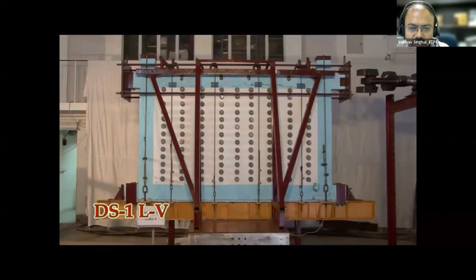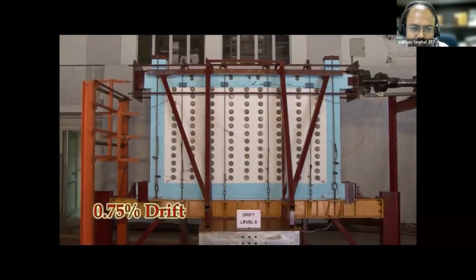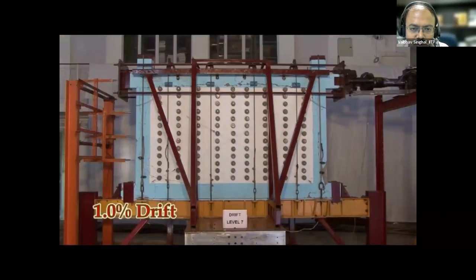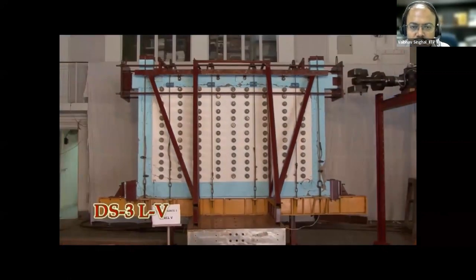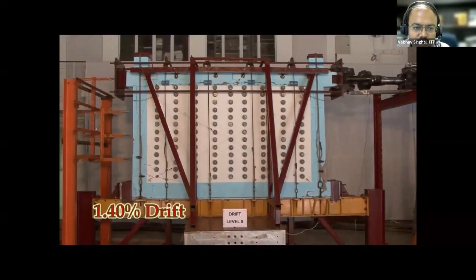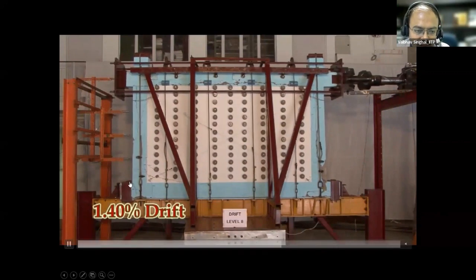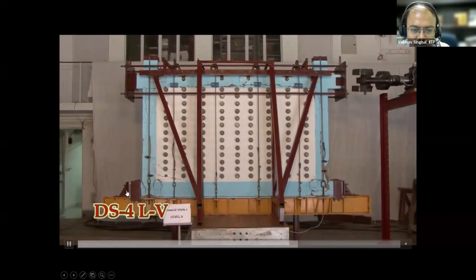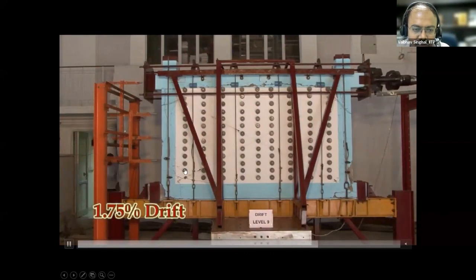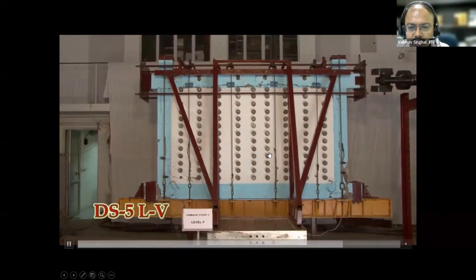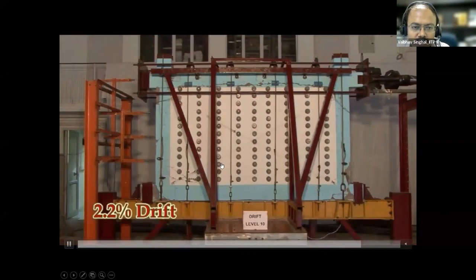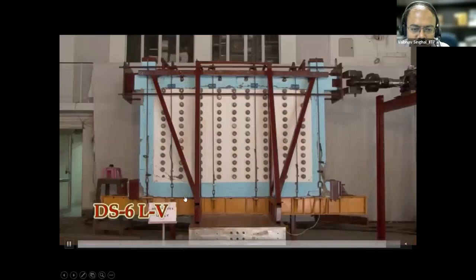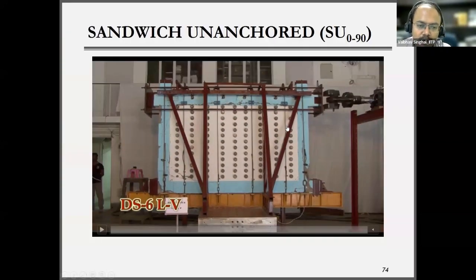The response was better than the control specimen, but we have seen that when there are no anchors, there was an early separation of the wall from the RC frame, the reinforced concrete frame. Now you will see here, if you look at the bottom corner, during the in-plane loading, the plaster along with the masonry is simply moving, and the frame is not. You can see there is a lot of slip, or you can see the debonding of the plaster.